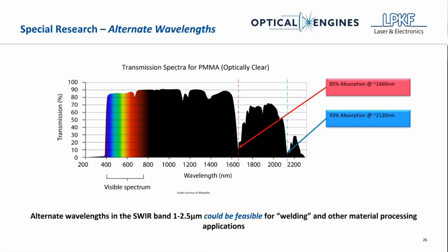And then if you look up here at the over 2 micron, you can see that even more absorption can be had. So this is more or less just to open your mind up to look at, okay, there are different wavelengths, different absorption rates in these plastics. It doesn't just have to be 1940 nanometers, although that is the more commercially available laser wavelength. But I'm working personally with a certain laser supplier to work on testing these different wavelengths. And there's a few people out there that have tested different wavelengths as well.